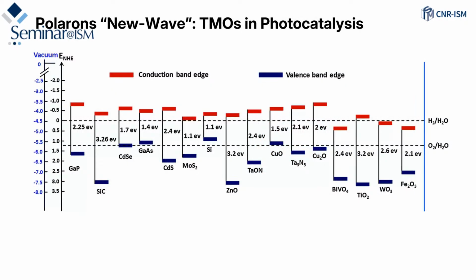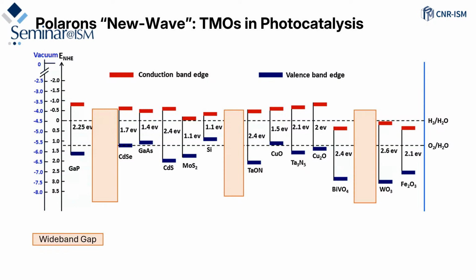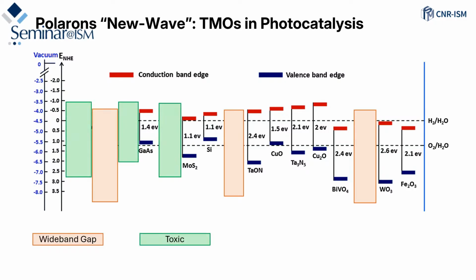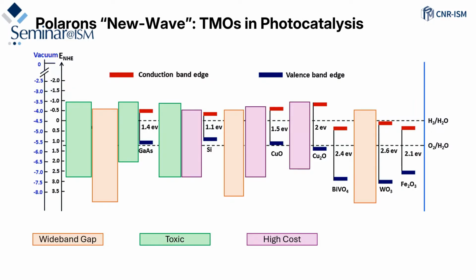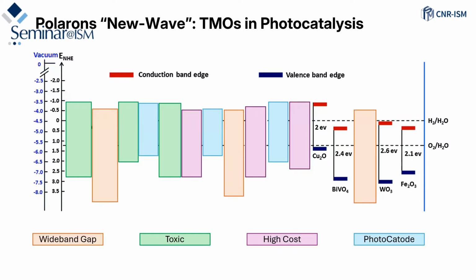On the other side, from the applicative point of view, this new wave of polarons comes from the necessity to understand why some of the transition metal oxides do not work as well as they should. So here is just to mention all the materials that can be involved in, for example, photocatalysis, for the water splitting reaction. If we take apart the materials which have a gap so wide that they cannot absorb enough light from the sun, we selected also the toxic materials and the high cost materials. And if you are interested in, for example, the oxygen evolution, so we just want to use photoanodes.